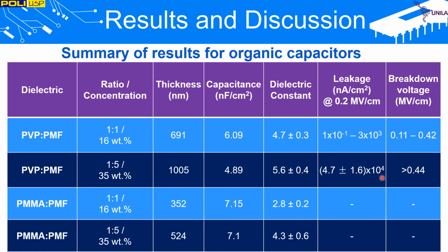However, this current was more uniform compared to devices with less PMF, and the breakdown voltage was also higher in this case. It is worth noting that a decrease in the concentration of hydroxyl groups in cross-linked PVP, as shown in FTIR spectrum, is also beneficial to diminish charge trapping at the dielectric semiconductor interface in OTFTs.